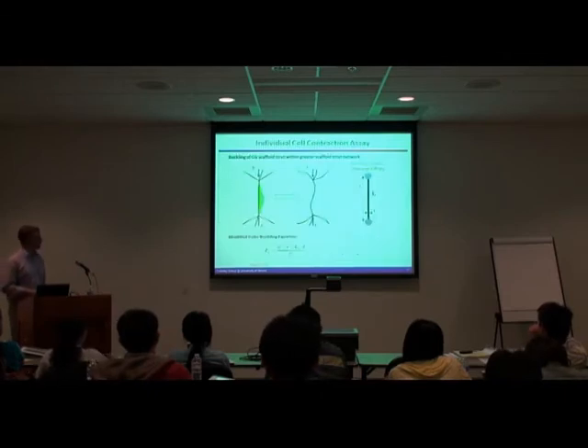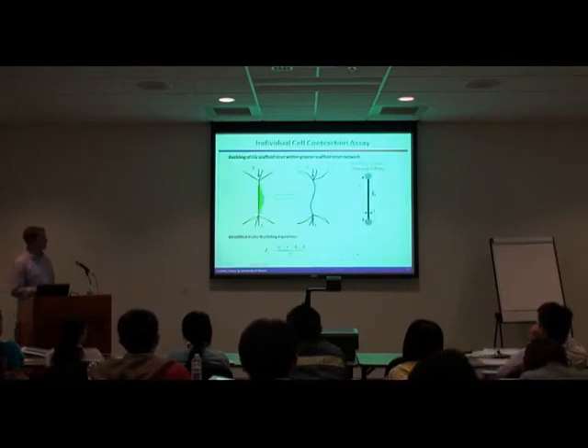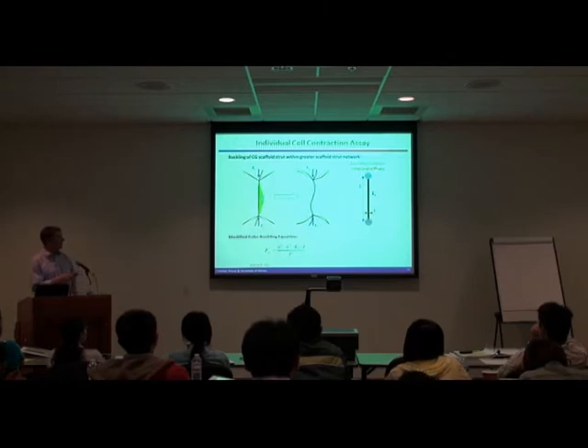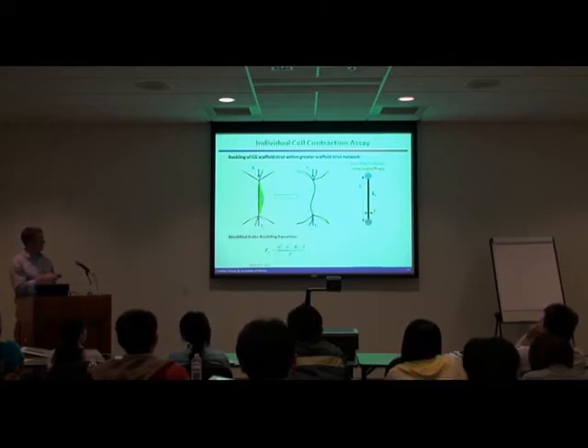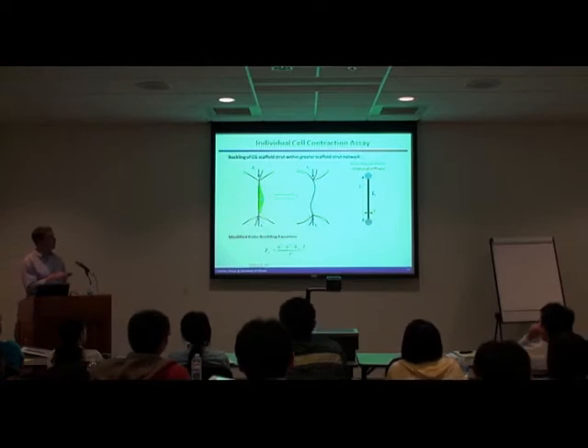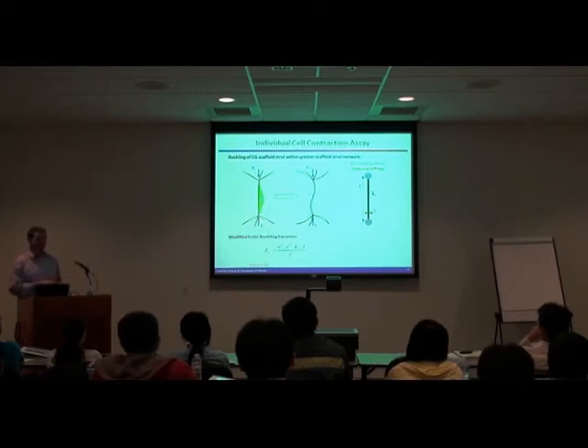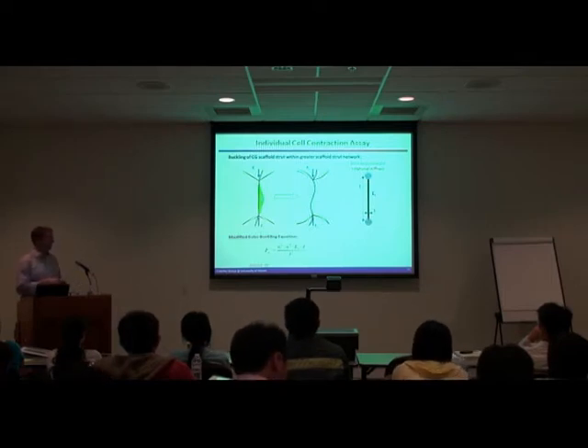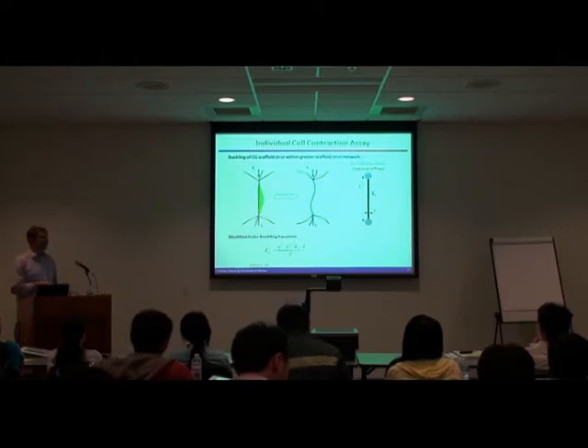But on to what I think is kind of a more interesting application of biosensing is if you actually want to make measurements of individual cell contraction events. And so this goes back to the video I showed a couple slides ago, where you had a single cell sitting in a fiber within the scaffold, and over time the cell contracted and the fiber buckled. And so there's actually, again, a modeling framework you could use. It's based off of a modified Euler buckling equation that has a prefactor out the front that's actually associated with the cellular material itself.